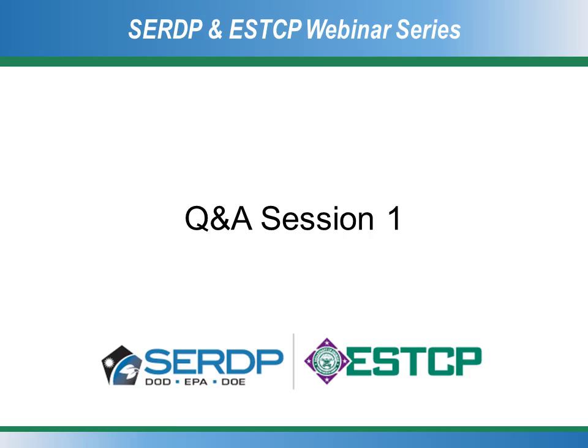John, how stable are the plating solutions you described? Do they need to be monitored often? Yeah, as I mentioned, the cobalt phosphorus process is very stable. You do monitor the cobalt concentration and the additive concentrations and the pH, but, for example, when we've been using a cobalt alloy for the electroformed bushings, in order to build up the wall thickness, you have to coat for about 36 hours, and the solution changes very little in that time.